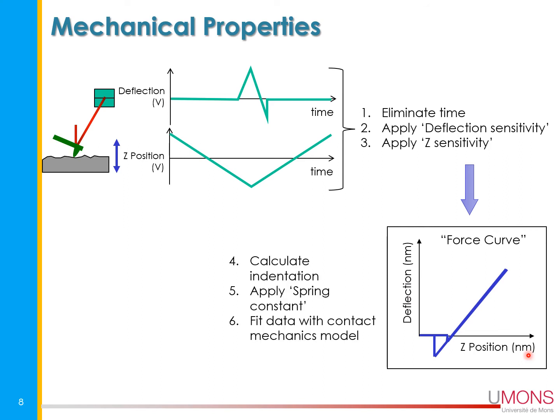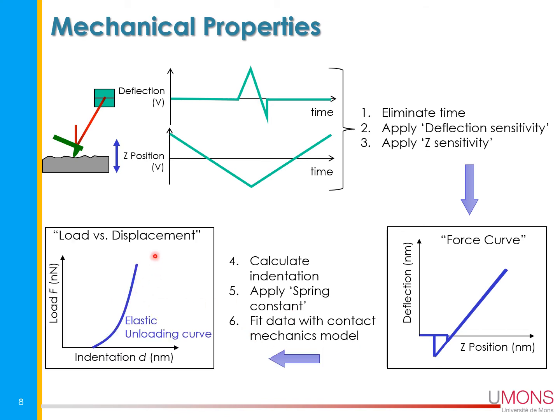Now, if you calculate out of that the indentation, and if you know the spring constant of your cantilever, and if you fit those data with a contact mechanics model, it's possible to generate what is known for people doing nano indentation, for instance, the curve corresponding to the load versus the indentation. And you have this curve, and you can fit it with the mechanical model to get different properties. For instance, here the rigidity modulus. This is the DMT model in this case.